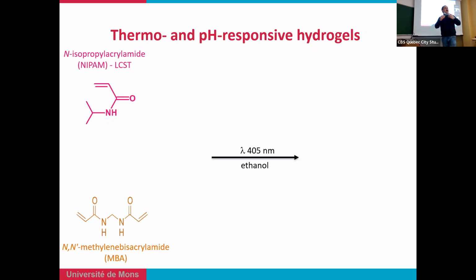Of course, as a hydrogel, you need to add a crosslinker to sustain the deformation in the presence of water. And you need to use the right photoinitiator applicable using 3D printing, related to the wavelength, which is more or less based on UV wavelength around 405 nanometers.